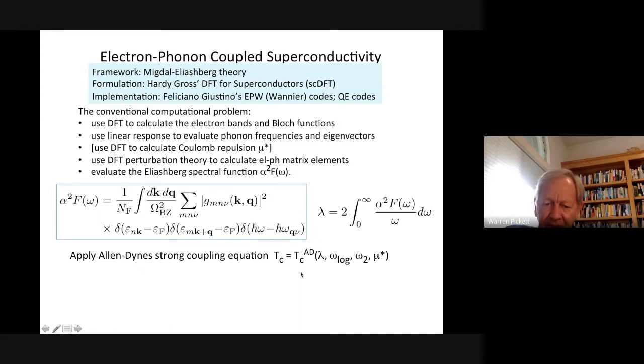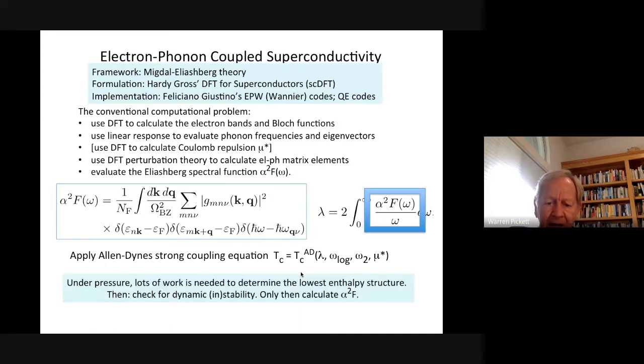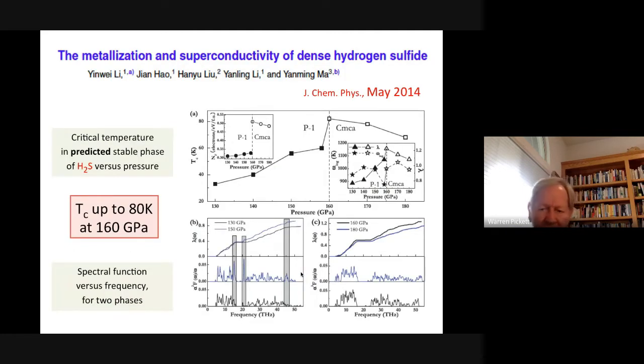So we're not going to do any heavy theory after this. So this is a paper that was almost right. Yanming Ma's group published this paper in May 2014. What they did was to put hydrogen sulfide, H2S, into their pressure cell. I'll show you the pressure cell in just a moment. If you notice, well, sulfur is just below oxygen in the periodic table. So this is almost like a heavy analog of water, H2S. It's better known as rotten egg gas. It's the stuff that really smells, but you can, of course, liquefy it and then put that in your pressure cell. And they studied the likely stable phases of H2S under pressure.